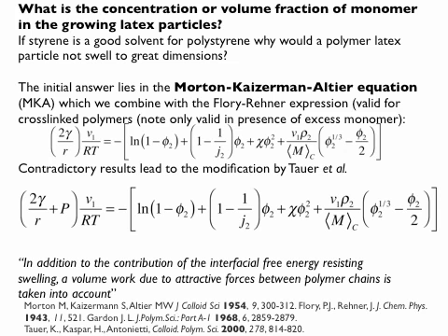So you can actually do some experiments and say, okay, if I know my entropic terms, which are basically only defined by the length of my polymer and the volume fraction, so that's easy to measure, the interaction parameter falls out of that. So for a system like polystyrene in styrene, you can look up what this parameter should be. So that's the first 3 bits.